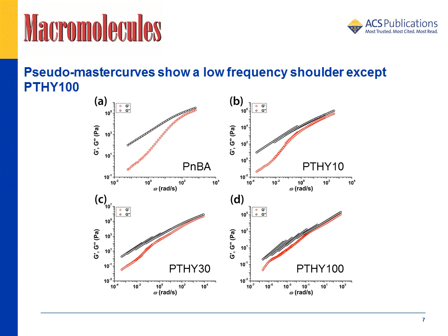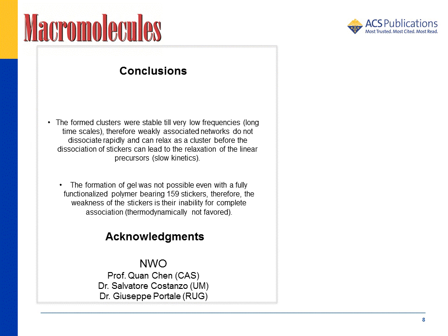However, the presence of nano-domains and phase separation of poly-n-alkyl acrylates is well known due to side chain incompatibility. In these four master curves, we clearly see that whenever the incompatible side chain is absent, the shoulder is also absent. In the case of PTHY100, we see this, and even the spacer between the thymine does not phase separate due to the bulky thymine group.